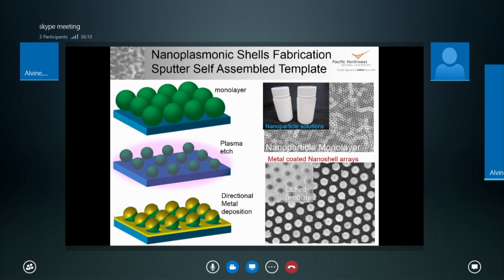So how are these made? They're made by a hybrid process. First off, start with wet deposition of a monolayer of polymer nanoparticles, which we can deposit over hundreds of square feet in a roll-to-roll method. Then we do a plasma etch of the nanoparticle monolayer—this is the starting point in the upper figure, and then we etch them, as you can see in the insert of the lower figure. Then we deposit a metal on it with directional metal deposition in a vacuum process, and that's what this lower figure shows.